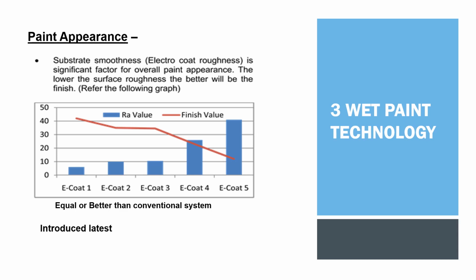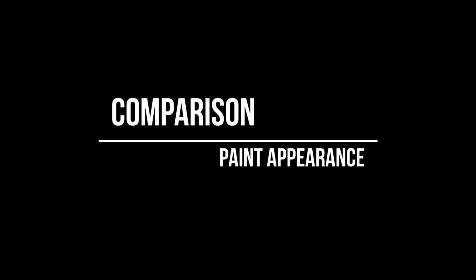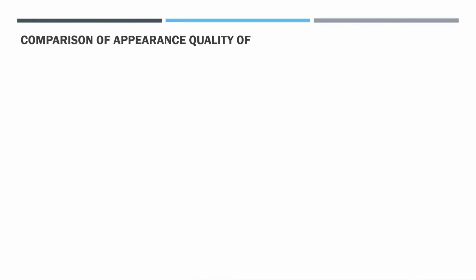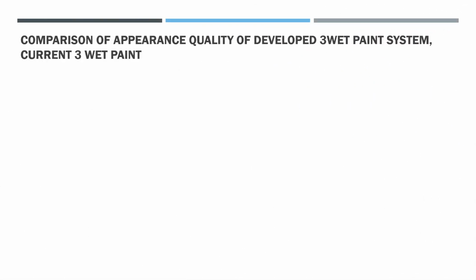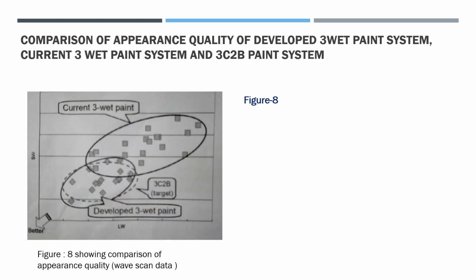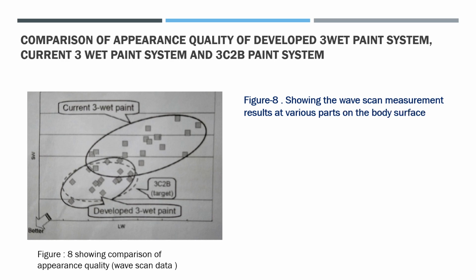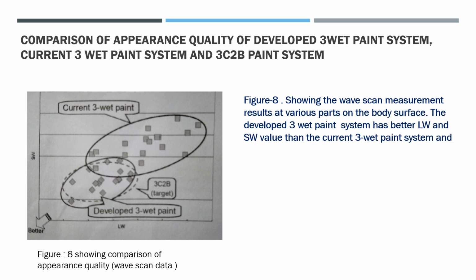Paint appearance. Substrate smoothness, the E-coat roughness RA value, is a significant factor for overall paint appearance. The lower the surface roughness, the better the finish. Comparison of appearance quality of the developed 3-wet paint system, the current 3-wet paint system and the 3C2B paint system. Figure 8 shows the wave scan measurement results at various parts on the body surface. The developed 3-wet paint system has better LW and SW values than the current 3-wet paint system and almost the same or better than the 3C2B paint system.